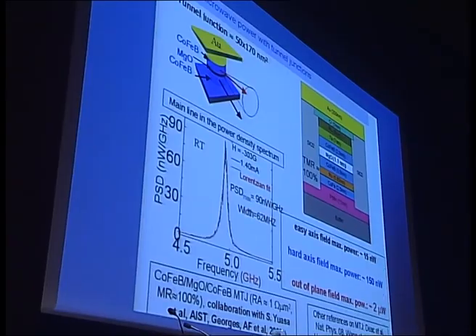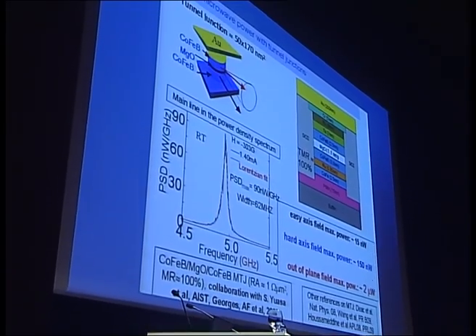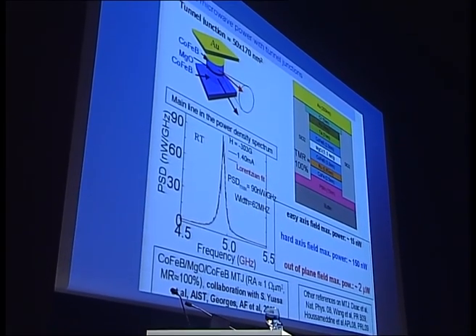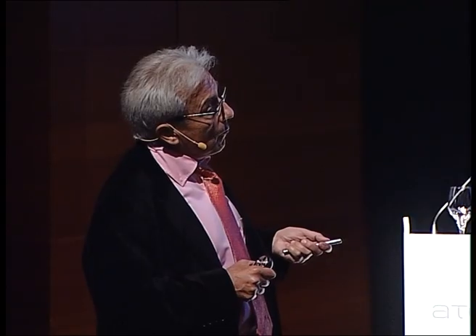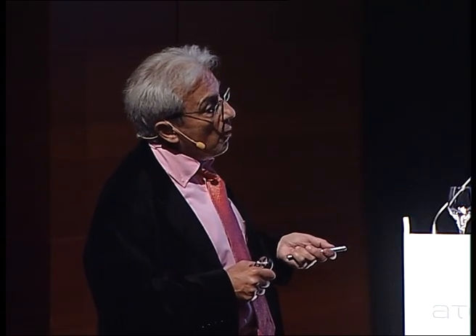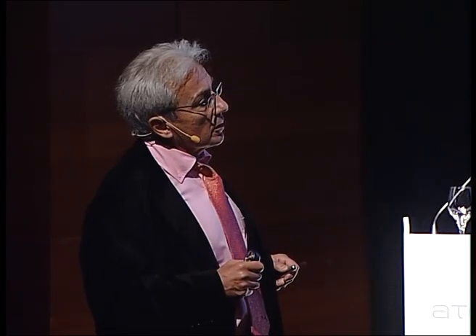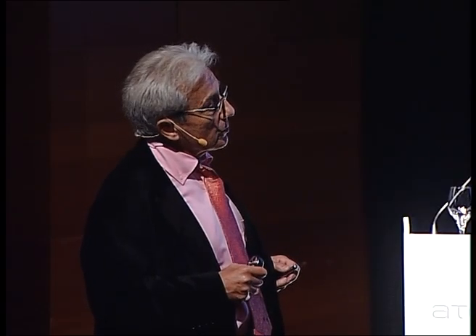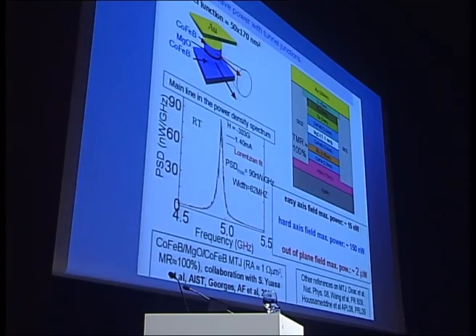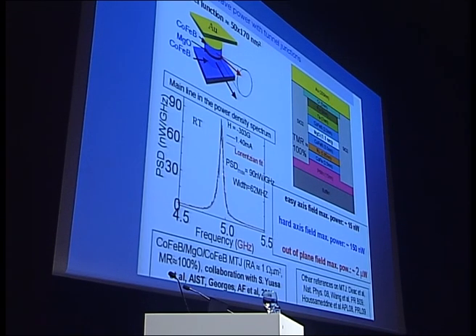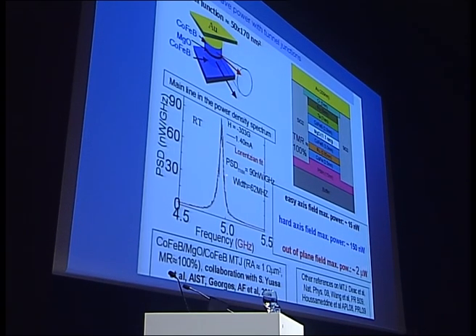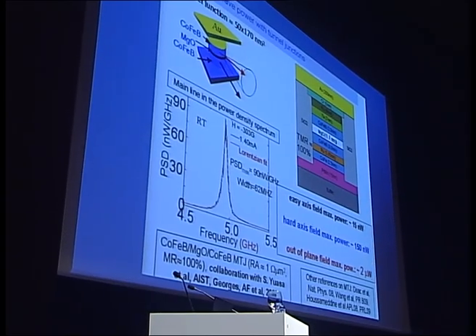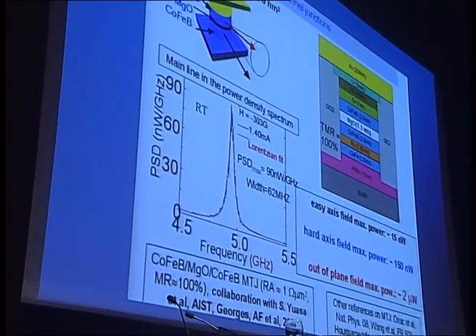For a metallic tri-layer, the power is in the picowatt range, and for tunnel junctions we have obtained microwave power up to 2 microwatts, which is close to what is needed for applications. The disadvantage of this tunnel junction is still that the width of the emission is too large, 62 megahertz, and 1 megahertz would be ideal.